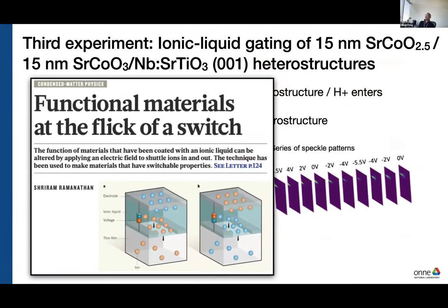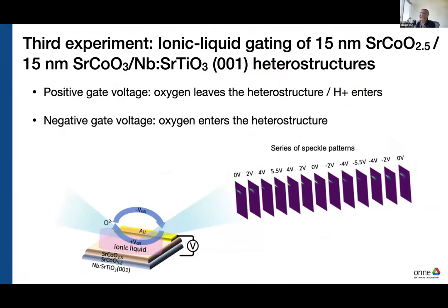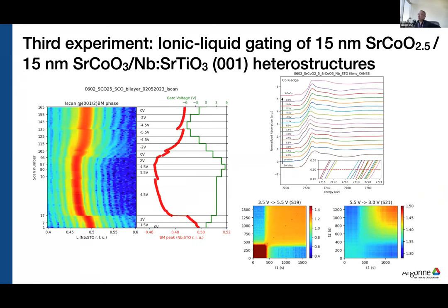I'll just end by saying that we're now doing experiments with strontium cobalt oxide, but these are bilayers, and we are playing with ionic liquid gating. This was something that Sriram had been talking about in a previous paper, and Puyu, his group and others have been playing with this system. Now we are playing with this system with dynamic studies using coherent X-rays. Here's just some of our initial data.